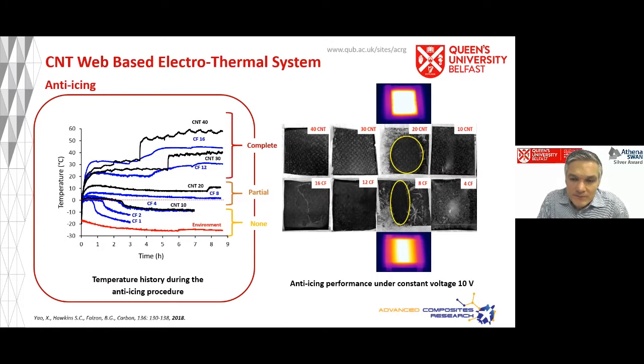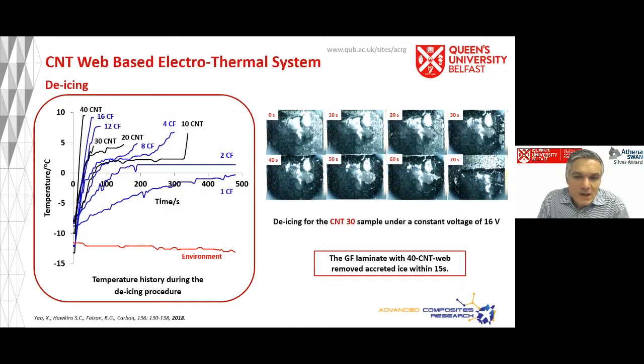So we've also done an analysis on the power requirements, which also shows that the system is very efficient. We've also then looked at de-icing, where we basically froze the water over the sample, and then we mounted the sample vertically so that we can have gravity helping to remove the ice once we started heating the element.